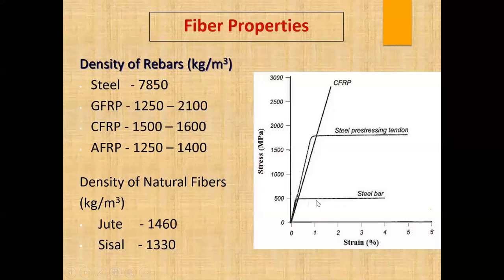The steel bar will have enough ductility, or at least the required ductility, especially mild steel. And the pre-stressing steel also. If you make a comparison between these three, at failure, the failure strain for CFRP is very low as compared to the steel bar. That's one of the major drawbacks of this particular material when used in civil engineering applications. The failures are going to be very catastrophic.